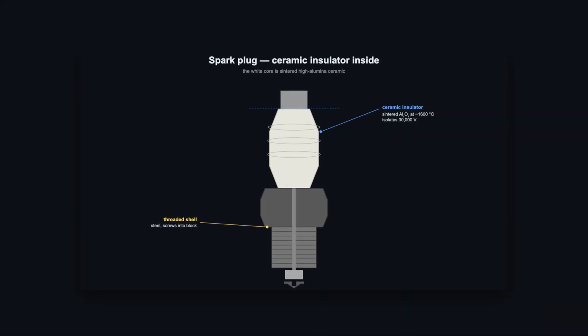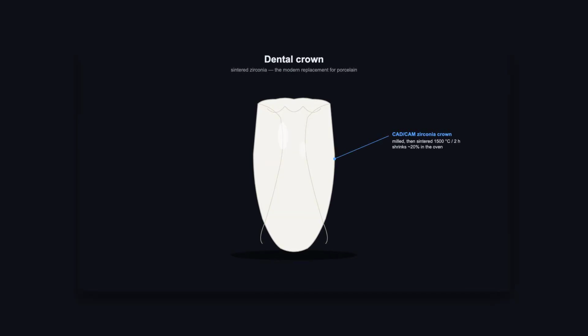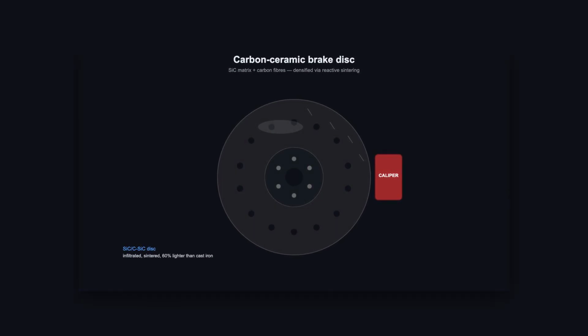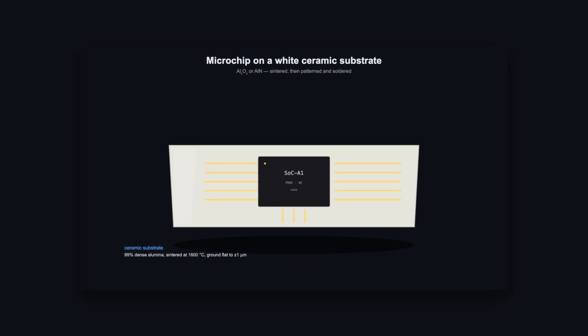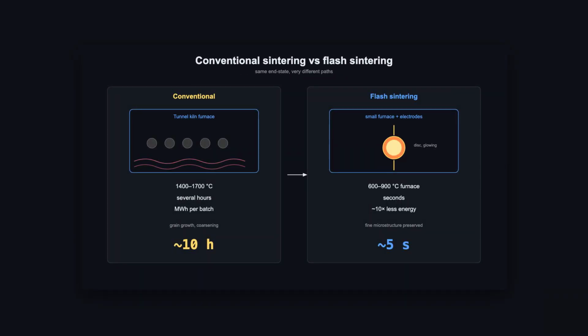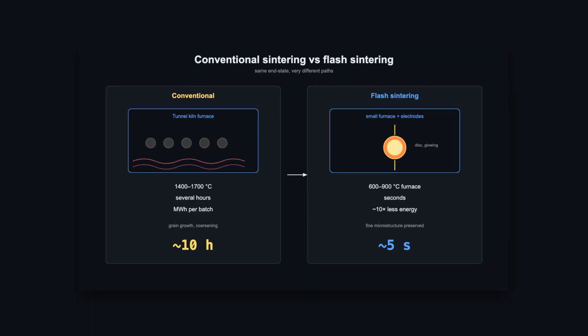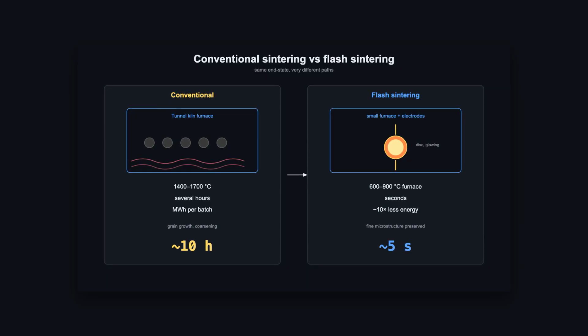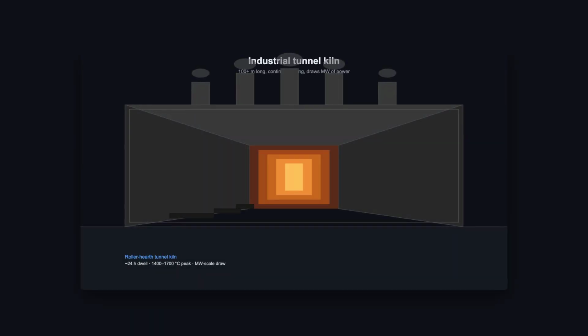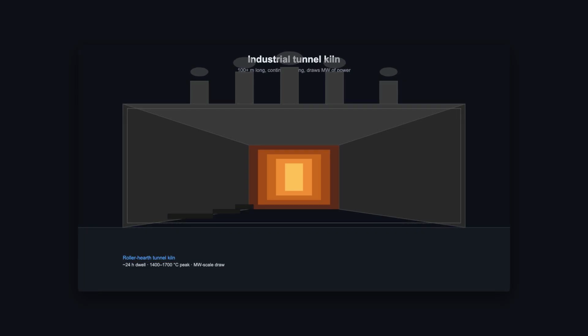It is how the white insulator inside a spark plug is made. How dental crowns are made. How ceramic brake discs are made. The white substrate under nearly every microchip in the room you are sitting in, sintered. It is, depending on who you ask, the second or third most energy-intensive step in industrial ceramics. A modern sintering furnace can draw the power of a small town for an afternoon. And it runs hot, 1400 Celsius for zirconia, 1600 for alumina, 1700 for the hard stuff. For hours, sometimes a full day.